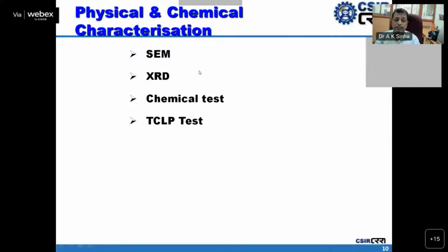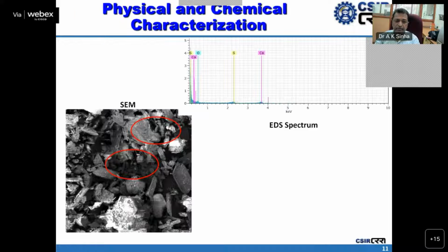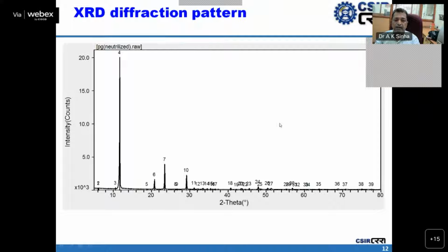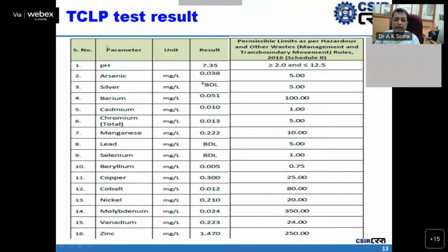These are the physical and chemical tests that were carried out on phosphogypsum based materials. This is the SEM and this is the EDS, and this is the XRD. A TCLP test was also carried out to know the hazardous nature, and it was found that as per the Ministry of Environment, Forest and Climate Change Guidelines 2016, all heavy metal concentrations are within the permissible limits.